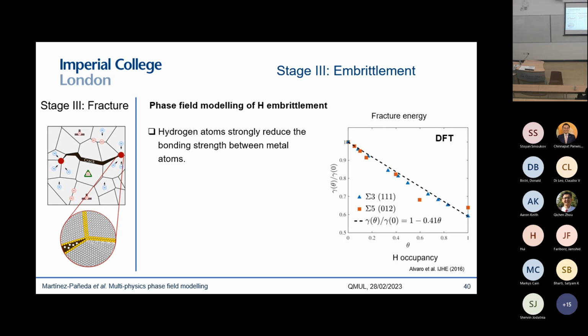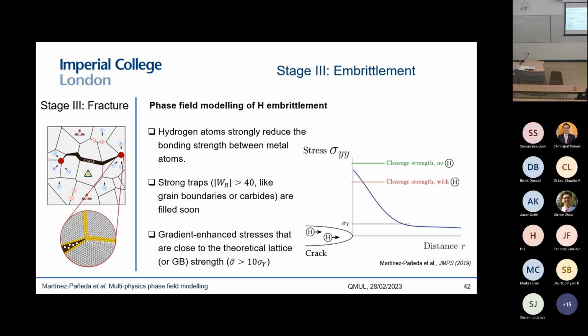And when this is the case, we know from our atomistic calculations, we're going to have a very significant reduction in fracture energy and bonding strength. And when you put all these things together and you combine this with some microscale plasticity models that I don't have time to discuss, what you see is that in the absence of hydrogen, your stresses are not high enough to reach the cleavage strength or the grain boundary strength.